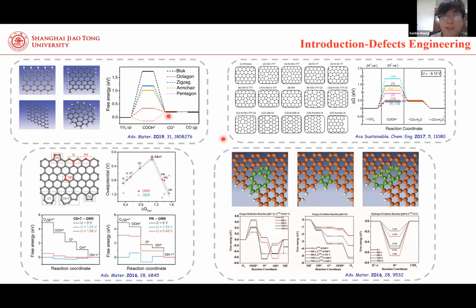However, the high specific surface area of the porous carbons originates mainly from the topological defects. A few researchers found that topological defective structures such as octagon, heptagon, and pentagon containing sp2 carbon species can act as active sites. Although such studies are very limited, this inspired us to develop topological defect-enriched porous carbon for catalysis. So far, many physical methods have been developed for creating topological defects in carbon materials. However, these physical methods can only be used for very localized areas and can't be used for large-scale preparation.